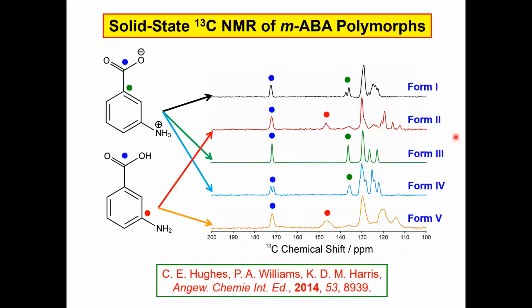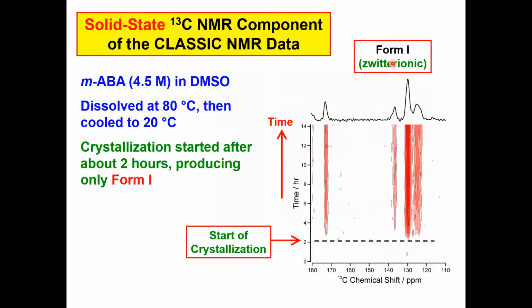Meta-aminobenzoic acid has 5 known polymorphs, as shown there, and they're clearly distinguished on the basis of their solid state NMR spectra. Here's the solid state component of the classic NMR data. What we can see in this experiment, there's actually a delay time of around 2 hours where there's no signal in the solid state NMRs. There's an induction time before nucleation happens. This is quite common in crystallization.